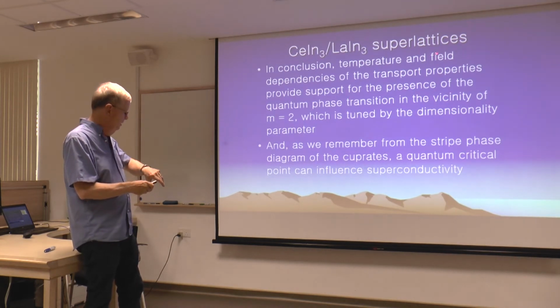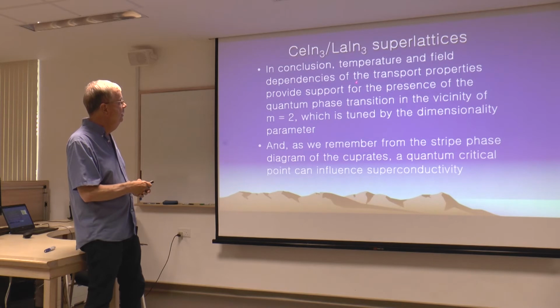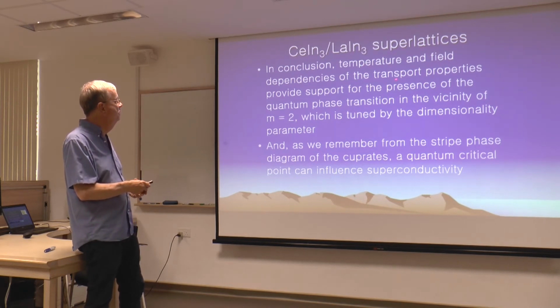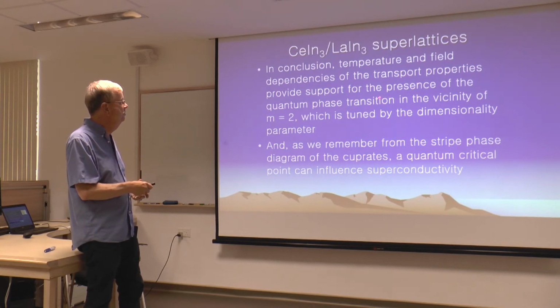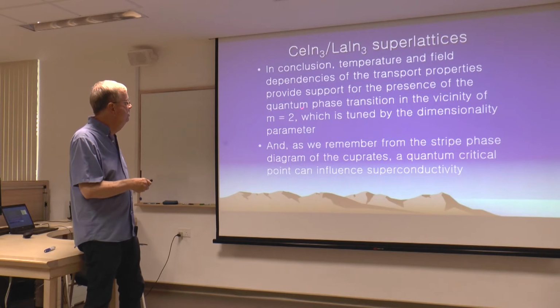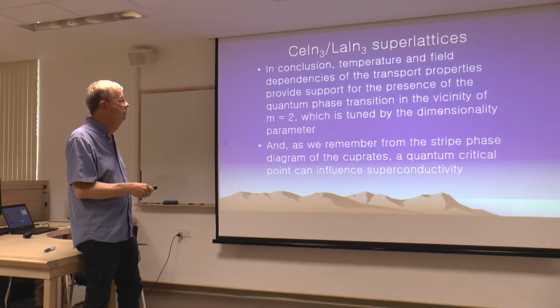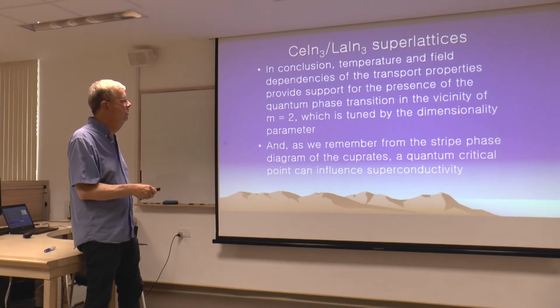So what we've seen is that the temperature and the field dependencies of the transport properties provide support for the presence of a quantum phase transition at the vicinity of where the cerium indium-3 looks two-dimensional. And so we've tuned it not by doping, not by pressure, not by field, but we've tuned it by dimensionality. And it's a very powerful tool, particularly if you can make clean samples.